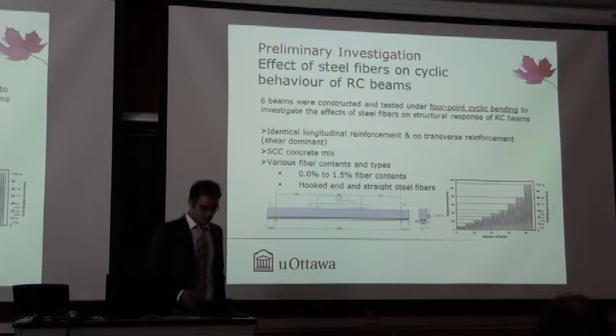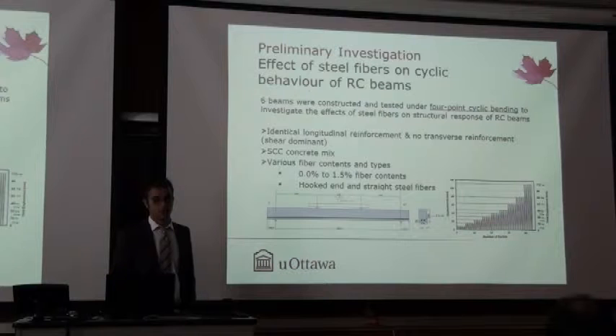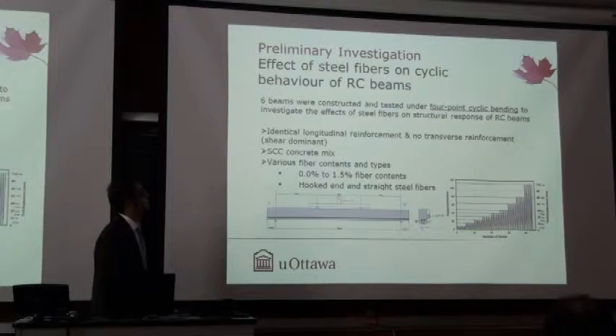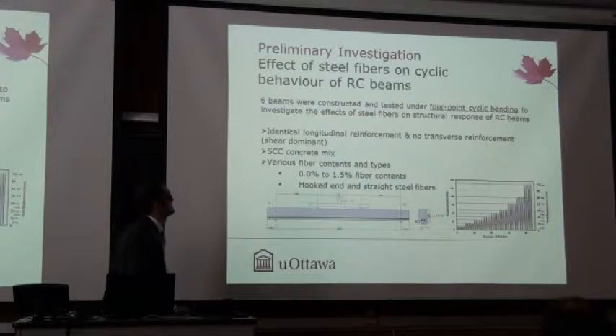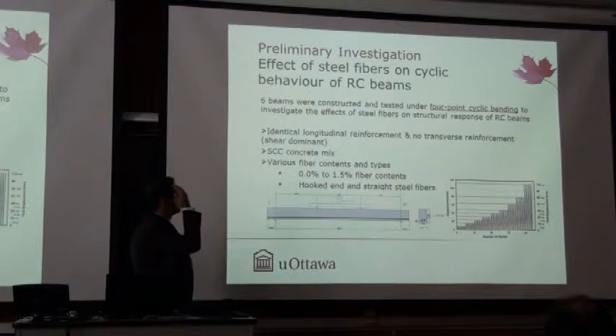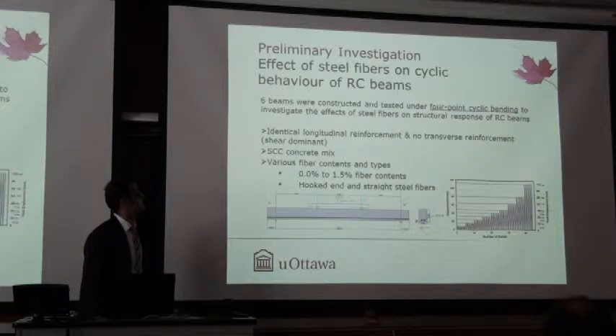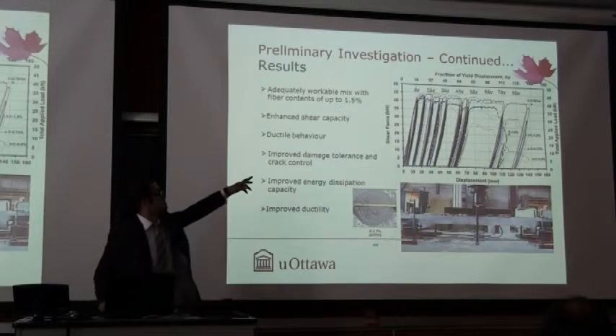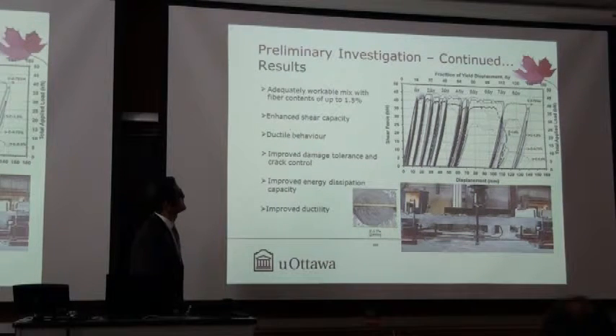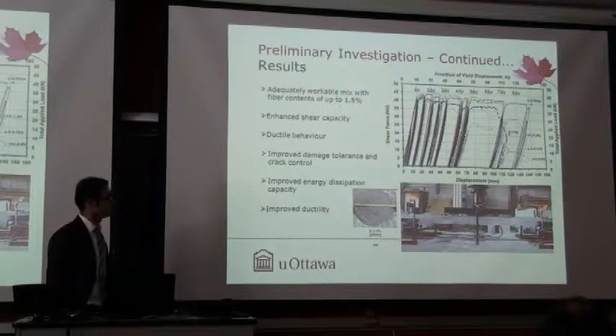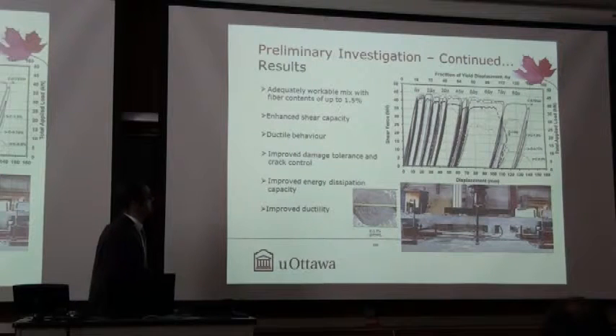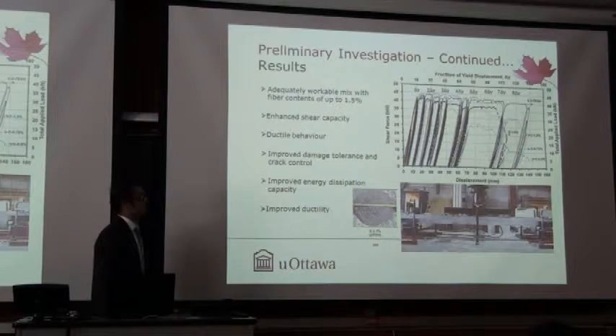Before starting my main experimental program, we did some preliminary investigation. We tested 6 beams with different steel fiber contents and different fiber types. We used hooked end and straight steel fibers, and 0% to 1.5% fiber contents. It was a cyclic loading test, so it was loading and unloading in one direction only. And here you can see the cyclic load displacement curves. We observed a significant improvement in the shear capacity of the beams because of the steel fibers. We saw an improved energy dissipation capacity of all beams reinforced with steel fibers, improved ductility, improved damage tolerance and crack control, and also more ductile behavior.